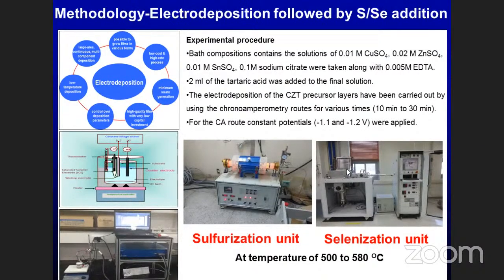Otherwise, there is another method where you take copper, zinc, and tin layer by layer, and after that you anneal it. Okay, that setup is called the sulfurization setup, and another setup is the selenization setup. This setup has sulfur powder inside here, and here the selenium powder is inside.